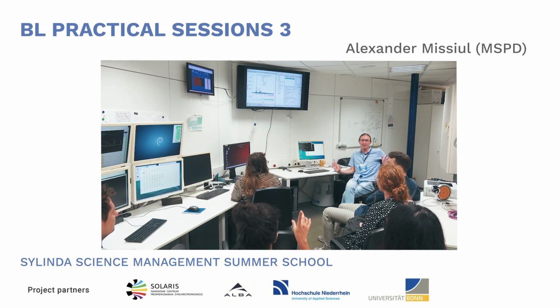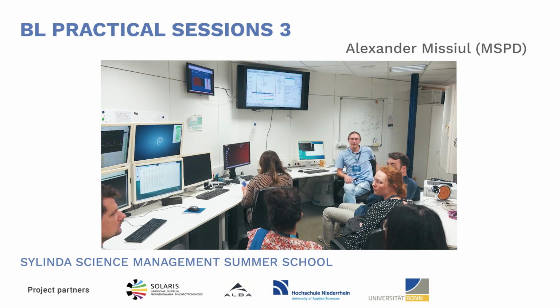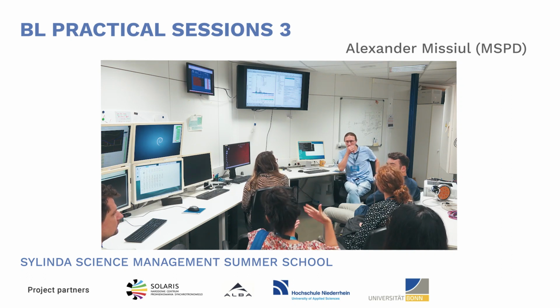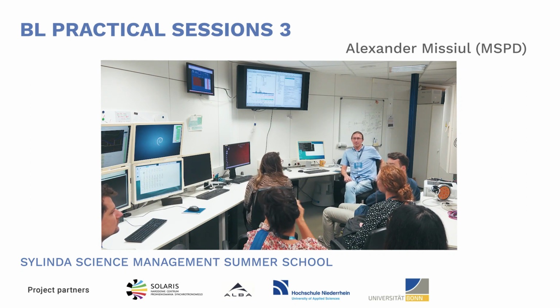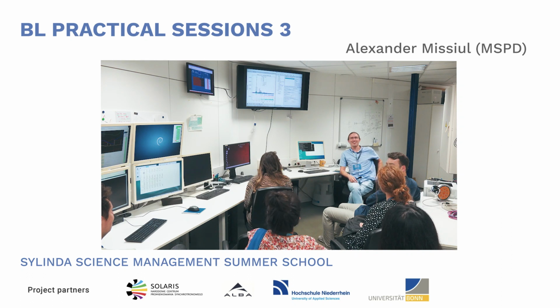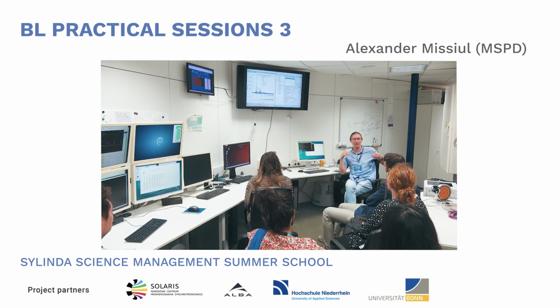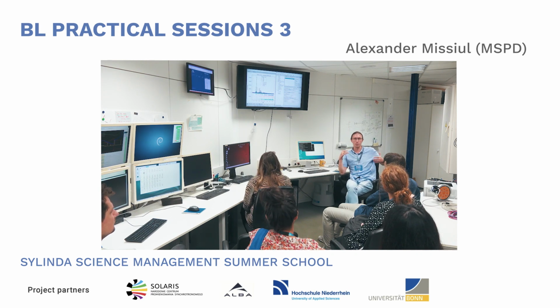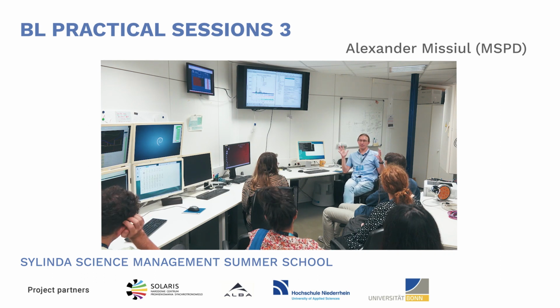For the refinement process, for all the steps that you did, do you have a path to follow, or are you just changing things randomly? No, it's experience. Yeah, it's a bit of experience, or a bit of knowledge. So there is a logical sequence. You start with parameters that affect the pattern a lot and are more stable, and then you go to more tiny details. Normally you start with background and overall intensity. Then you add the lattice parameters and maybe the phase fractions, and then you go to atomic parameters and the peak shapes. Usually it's more or less like this, and then it depends.